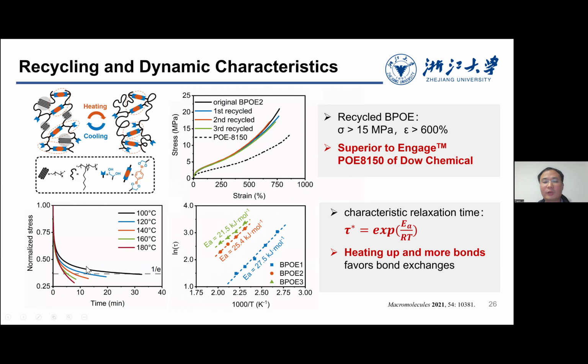And we also studied the characteristic relaxation of this kind of polymer. If you heat up, you can have more bond exchange. These bonds will favor exchange because these groups at a high temperature can exchange with the neighborhood. And in this way, they have a relaxation. This relaxation is dependent on the temperature. At high temperature, the relaxation time is short. And in this way, we can calculate the activation energy of the relaxation process. And here we find that with more diol groups remaining, the activation energy becomes lower. You can see here from BPOE1 to 3 the activation energy gets lower because more diol groups remain.